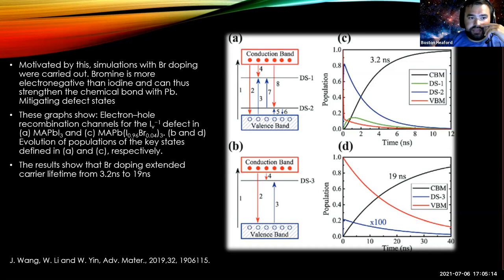These graphs show electron-hole recombination channels for the negative iodine vacancy defect in pristine methylammonium perovskites and the doped methylammonium perovskites. The evolutions of the populations of the key states are shown as well. They show that the bromine doping extended the carrier lifetime from 3.2 nanoseconds to 19 nanoseconds, which is a pretty significant increase. Again, the bromine doping can increase the carrier lifetime, which is good for the system.